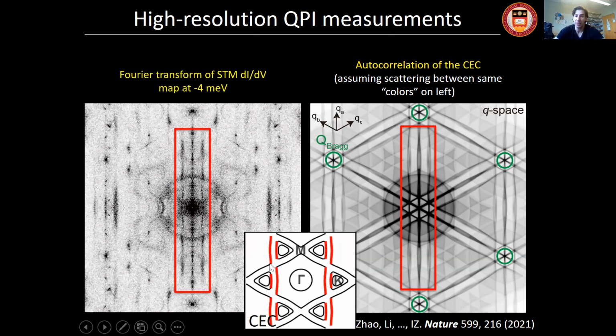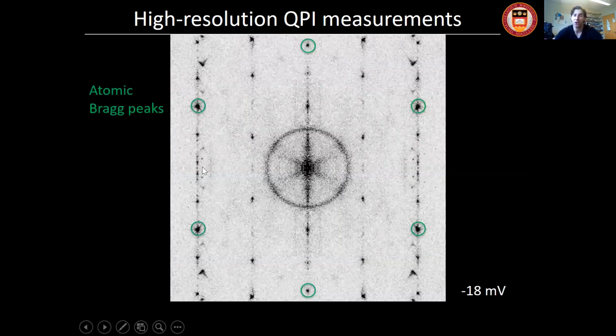Okay, so if you assume scattering between these, you're going to get the scattering wave vectors that we see in STM. So these are, again, vanadium bands. So based on theoretical calculations, we know these bands are primarily characterized by these Kagome vanadium plane bands. So it just allows us to get a glimpse into this Kagome structure and also see that the band structure is renormalized. So we now have this C2 symmetry of the electronic band structure as well.